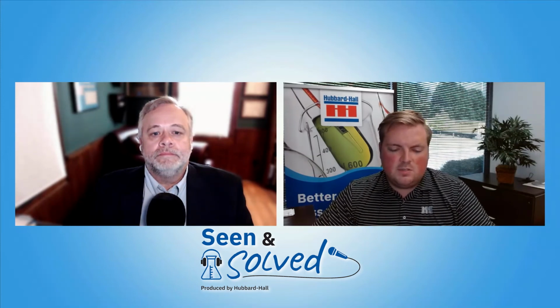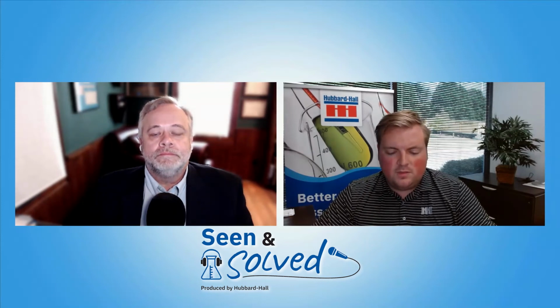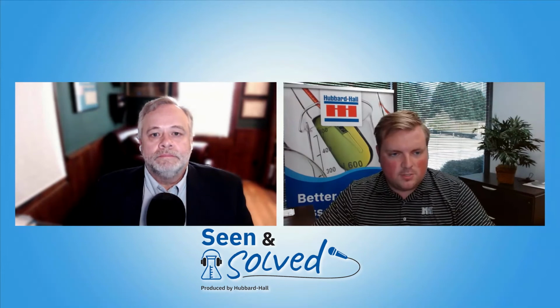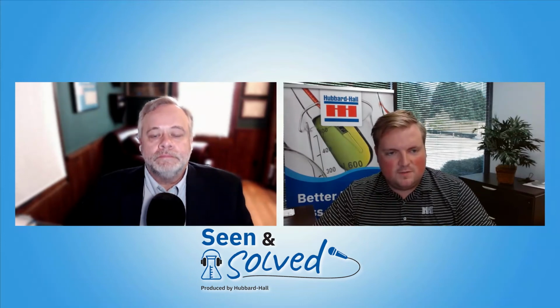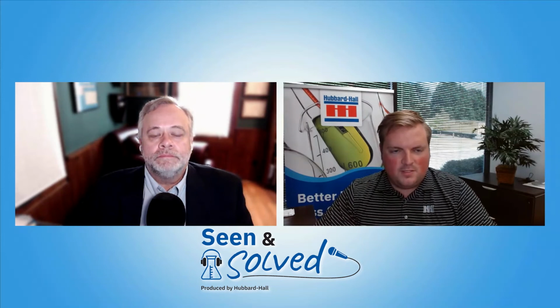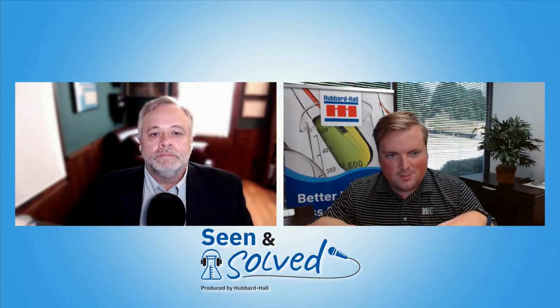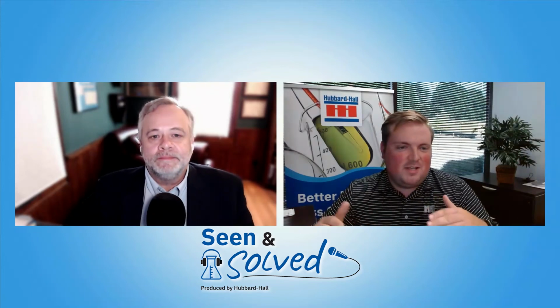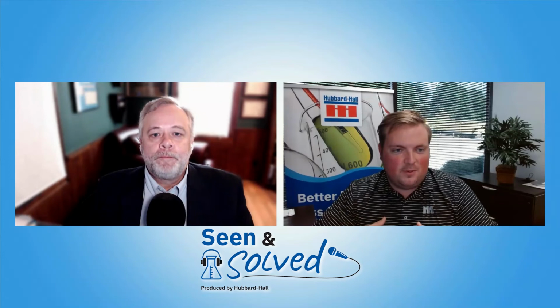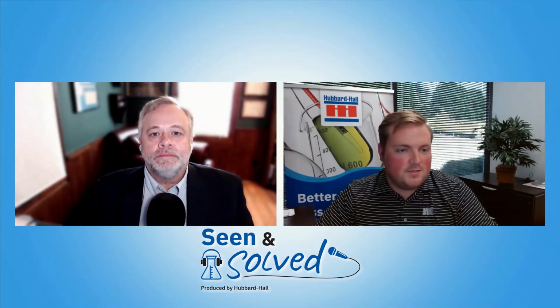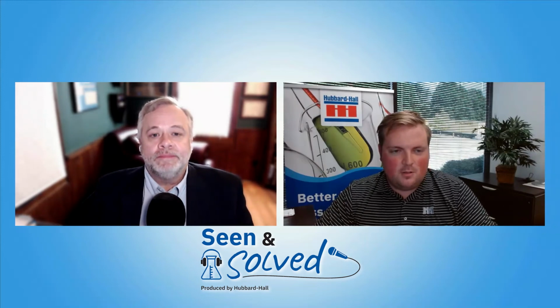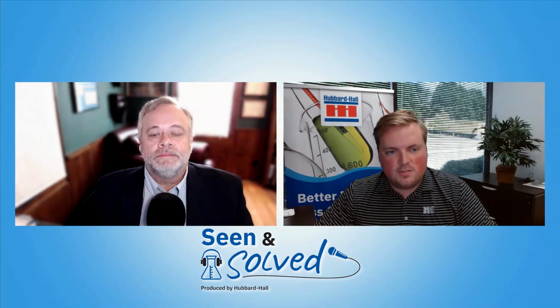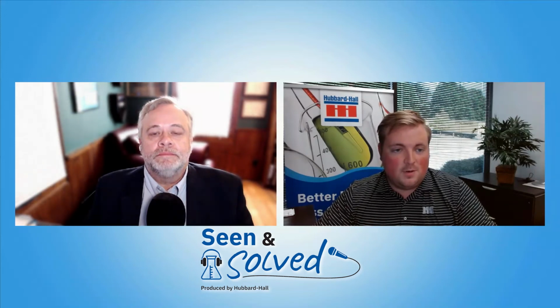One of the differences in terms of the crystal structure is that with iron phosphate, you're still putting on a microcrystal structure, but with a zirconium product it's much more on the molecular level, where you have this modified zirconium molecule that seeds into the surface of the metal at a much smaller level and provides microstructure adhesion. Imagine it like sandpaper grit. Rather than a 200 grit, with zirconium it'd be akin to using a 2000 grit. It's a much smaller level, but it still provides the variation in the surface geometry you need for the paint to properly adhere.